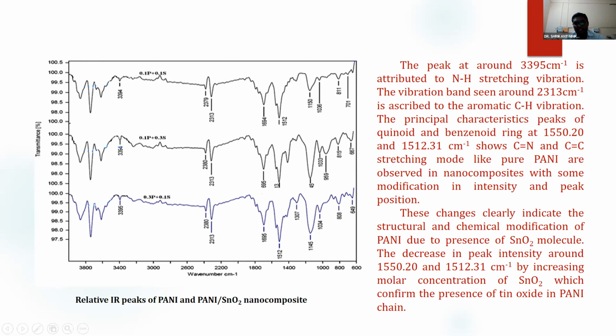That means the intensity of the peaks observed at 1550 and 1512 is slightly decreasing. This intensity decrease could be because of the higher concentration of SnO2, which again confirms the presence of SnO2 in the polyaniline.